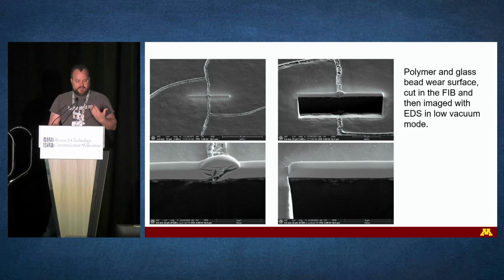This was a piece of polymer that is put into a water well with a bunch of glass beads to simulate sand, and they spin it around for a few months. And when we take them out at the end, we find a layer of silica or glass on the surface of the polymer. They were expecting that the glass would wear the polymer away, and what's actually happening is the beads are wearing each other away and depositing on the surface of the polymer. We did this with just regular SEM, but they wanted to know, well, how thick is this layer?